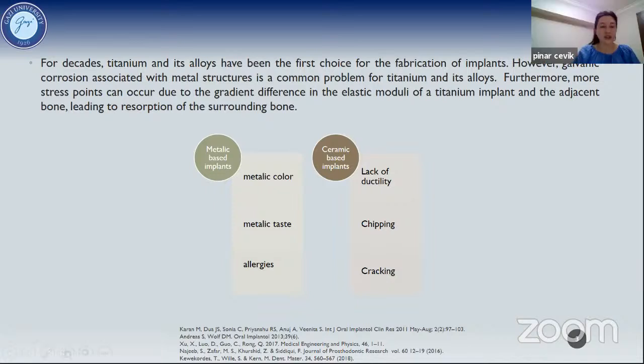galvanic corrosion associated with metal structures is a common problem for titanium and its alloys. Furthermore, more stress points can occur due to the gradient difference in the elastic moduli of the titanium implant and the adjacent bone, leading to resorption of the surrounding bone. This is the main disadvantage of titanium or metal-based implant structures.